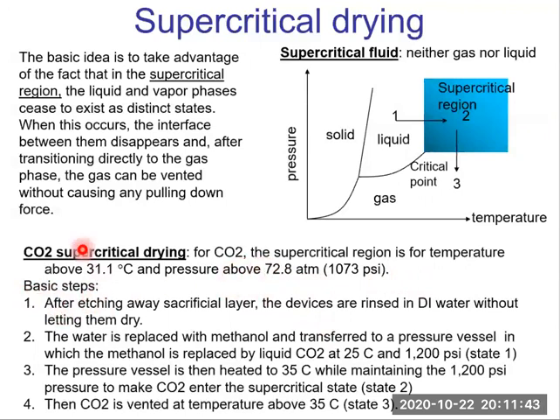Basic steps of CO2 supercritical drying. First, after etching away the sacrificial layer, the devices are rinsed in DI water without letting them dry. Right? It cannot be dry. If the devices are dry, then stiction already occurs. You cannot reverse the process. So we have to keep the devices wet.